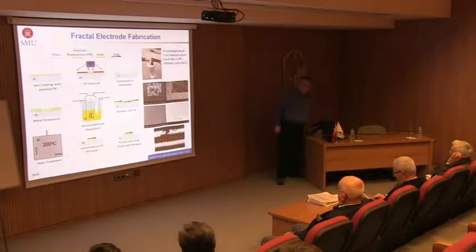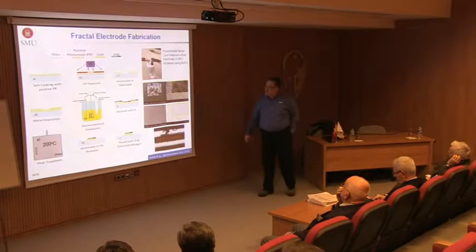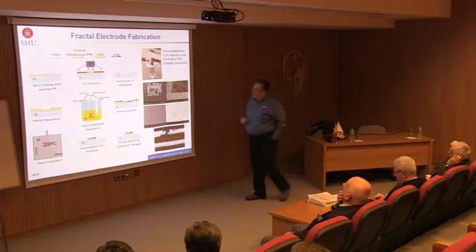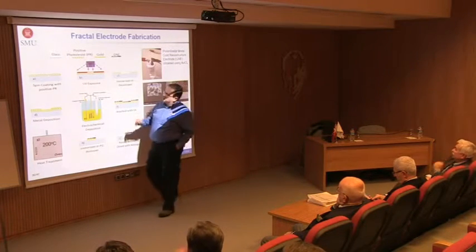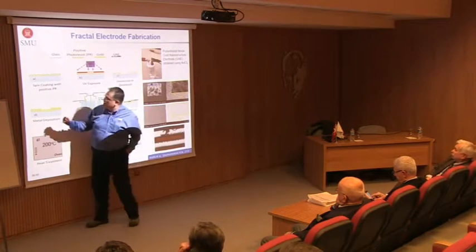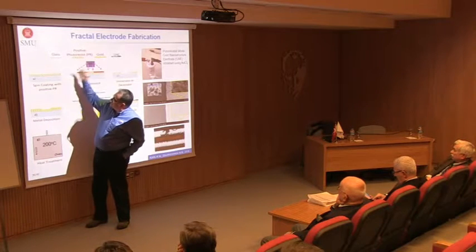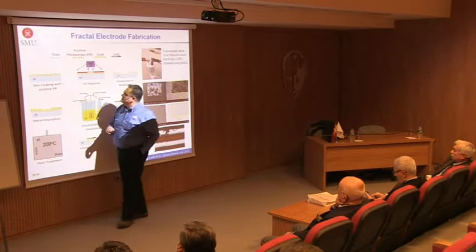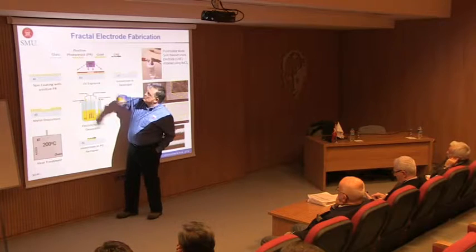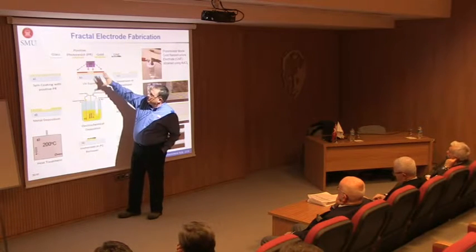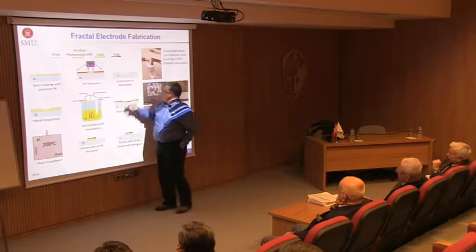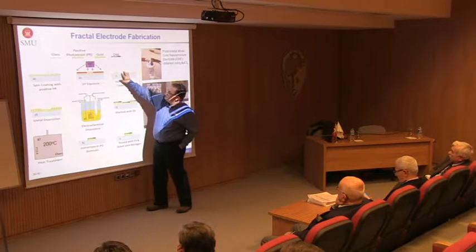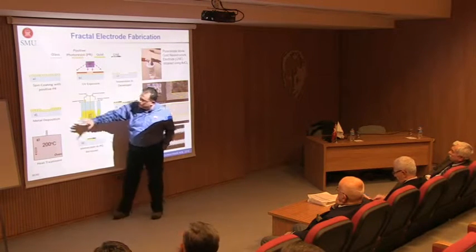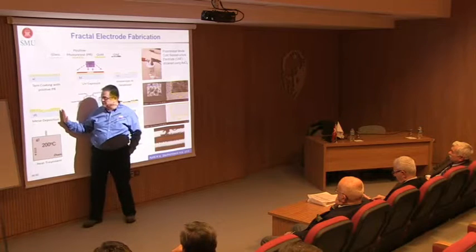So we learned different things. How can you make a fractal electrode? Well, it is a very standard photolithographic method that we used. We spin coat the glass with positive photoresist. We use a mask and a UV light, and we do a UV exposure, and then immerse it in a developer, so this part is gone, and then we do a metal deposition. So far, everything is standard.